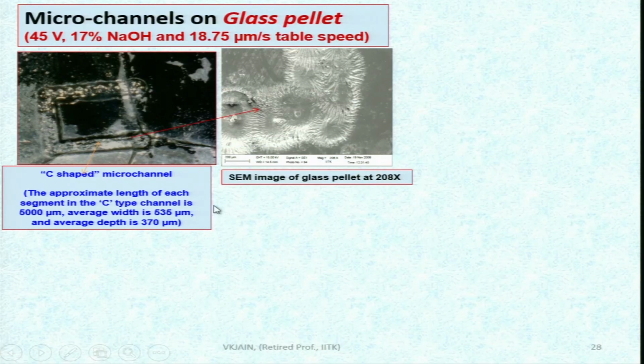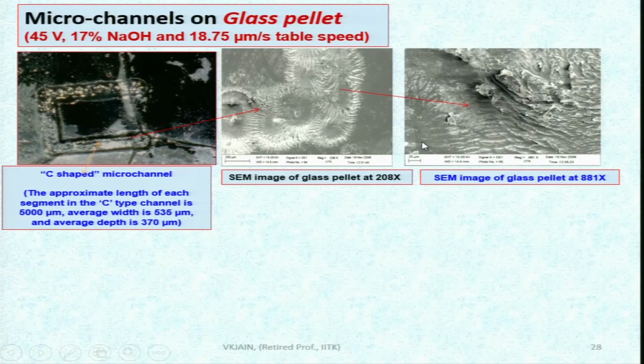Now, the important thing to see here is that this is the kind of surface you are going to obtain by this particular process, and this is not acceptable. So, one has to analyze it carefully, scientifically, and optimize the parameters, so that you really get a smooth surface over there. If you further enlarge this, you can see this is the way the material has been removed from here, and this is very rough, and these parts may peel off sometime if forces are acting. So, one has to be careful before really using them in real products.